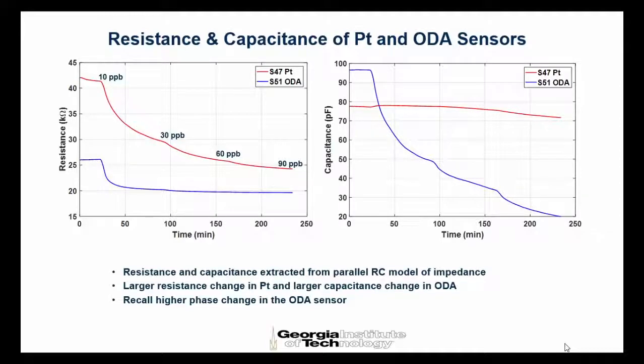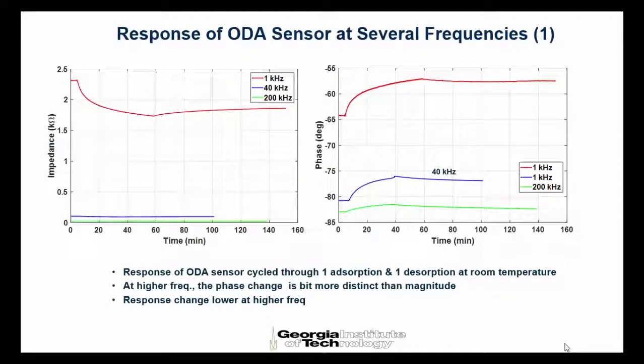Now you can also do calculation, right? This is an impedance, magnitude, and phase. What does it represent? It represents a parallel RC circuit. R is because of the nanotubes, and C is because of the layout of the interdigitated electrodes. So you can see that one responds well in resistance, the other one responds well in capacitance. So the same effect. And what we did is we looked at the frequency effect.